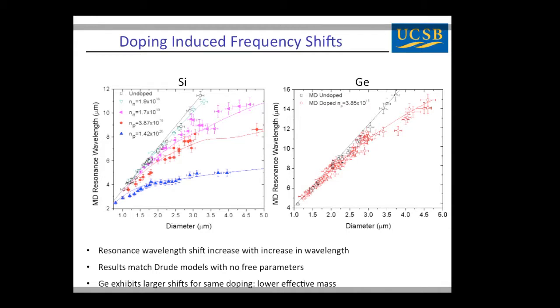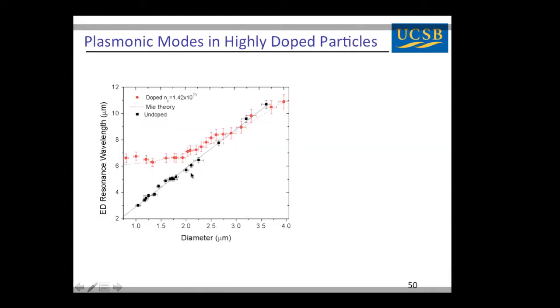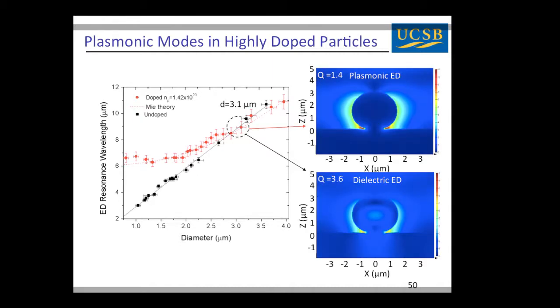We can also see that in the case of germanium, we get a larger response because of the lower effective mass. And if you look at this difference between our undoped and heavily doped particles, we can actually access a plasmonic regime where we have enough free carriers that our silicon does not behave like a dielectric anymore, but behaves like a metal.